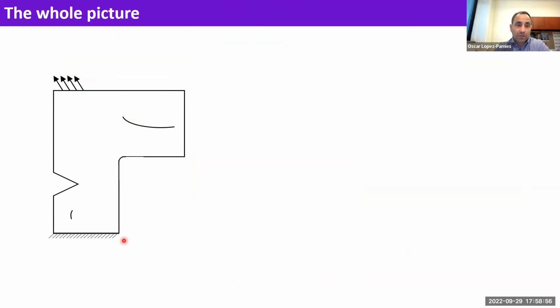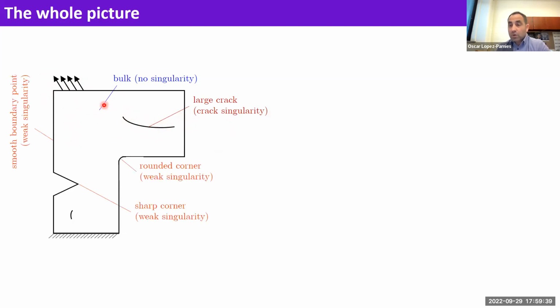So in reality, if you think of a structure, the following may happen. You may nucleate in the bulk, right? Think of this as, I don't know, some sort of beam with a fancy geometry. It is possible that you will create a crack because of the loads that you apply to it in what we call the bulk, away from any geometric singularity. But you may also have a large crack or many large cracks to begin with, right? Due to the manufacturing process, you may have cracks in the structure. So you have to account for the fact that you may nucleate from a pre-existing crack, or you may nucleate from the bulk. And, more generally, you have to take into account that you may have corners, which are also geometrically singular, but not as singular as a crack.